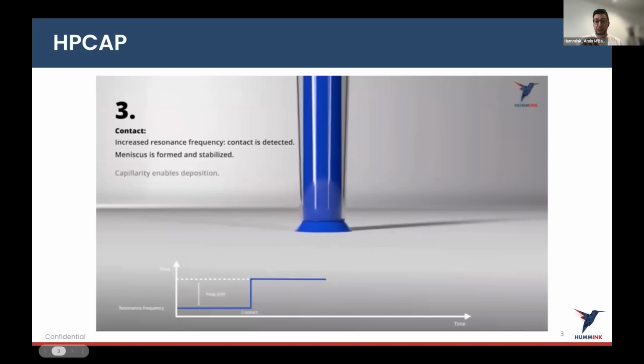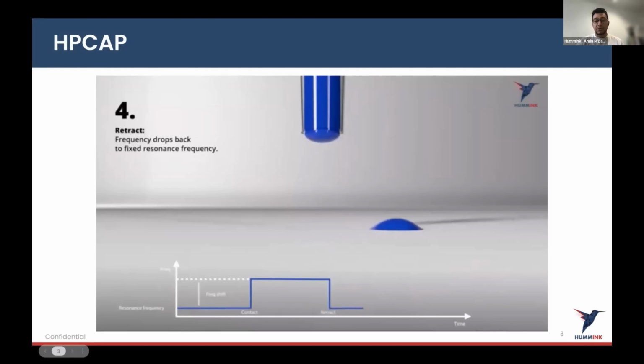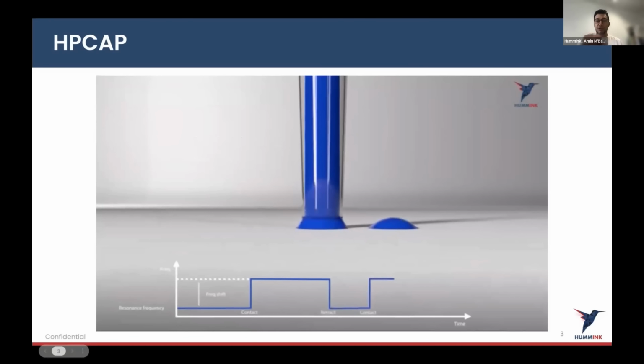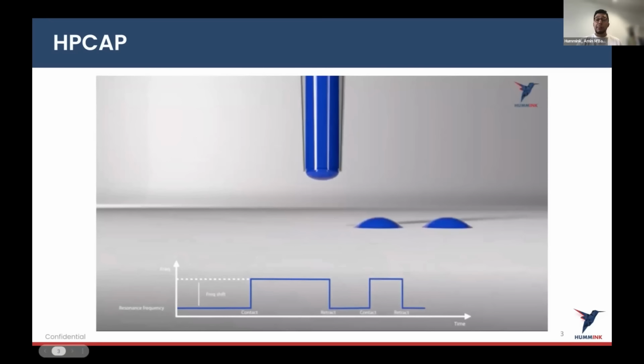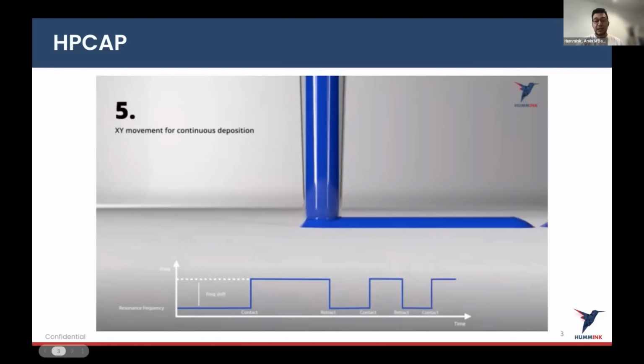Once that happens, we don't actually apply pressure, no UV, no laser. It's strictly based on the strength of capillary forces at these resolutions. So you can do drops like that. If you go up, the resonance frequency comes back to its previous value, and you just repeat that. So it's not drop on demand, but rather continuous printing, as you can see.